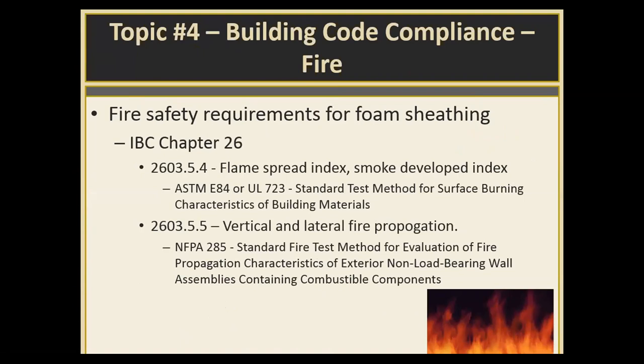The first is flame spread index, which is ASTM E84. Typically, you're looking at either less than 75 flame spread or less than 25 flame spread for foam insulations. And then NFPA 285, which is a large-scale multi-story test that measures fire propagation and movement in a vertical fashion from a lower floor room up a wall to a second floor area.